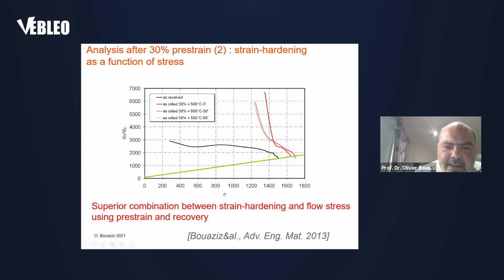You see in black the curve for the as-received material, and you see in red the results obtained after pre-strain and recovery treatment. What is interesting to note is that for a given flow stress level, for instance 1300 MPa, you have a strain hardening much higher than in the as-received condition. So this plot is useful to claim if you have improved the situation or not.